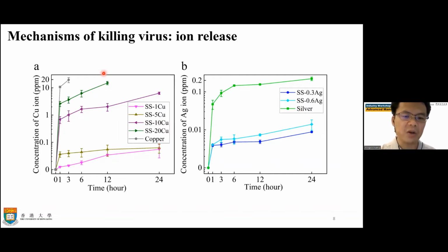Okay. So we expect that because of the copper ion release, this copper ion reacts with the virus or the bacteria, that leads to the death of the bacteria or the inactivation of the virus. You can see that for pure copper, a few hours later, the copper concentration is very high because it is pure copper itself, okay? But if you have a lower copper content, 1% copper, 5% copper, you see the copper concentration is low. With 10%, 20% copper, you see it reaches, within a very short time, properties very similar to pure copper. So that explains why a higher copper content can be a better antibacterial or antivirus stainless steel. We also checked similar for silver.